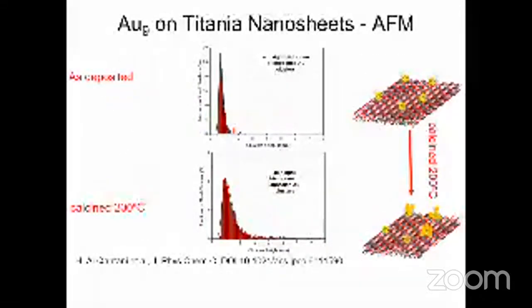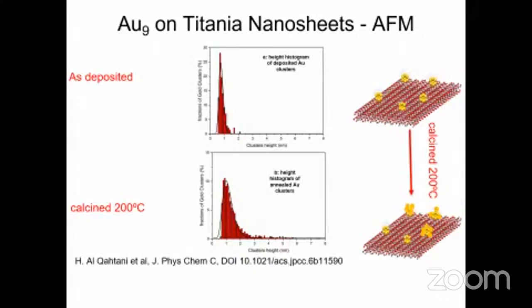The Gold 9 on titania nanosheet, as deposited, is around 1.2 nanometer in height. This is with the ligands. And when we annealed this gold nanocluster, it gets higher in height. This is the effect of annealing, and this is the aggregation degree for our Gold 9.